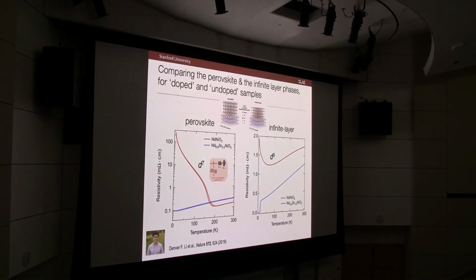So at that first stage, why did we land on 20% strontium? Well, we just said, if it's going to be like a cuprate, maybe that's where the dome is. And so this was just a flyer, let's say. I'll show you the doping dependence in a moment. So let's look at that perovskite form. This is what we grew in our growth chamber, the perovskite form of the nickelate, and as we just discussed, capped with strontium titanate.